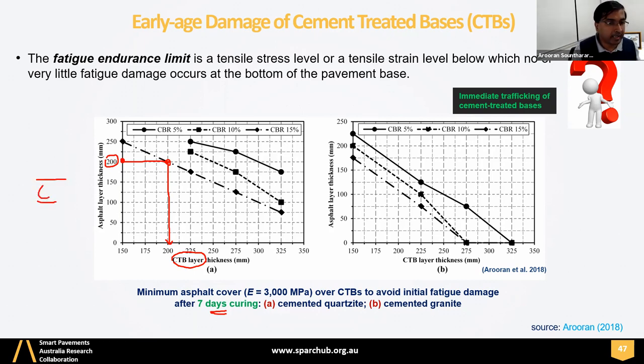that means your CTB layer is here, right? This is your cement treated base and you are constructing the asphalt here. This is an asphalt layer thickness, right? 200 millimeter. And then here, this is a subgrade, right? If the subgrade is 15 CBR, you want to construct a CTB which needs to be open in 7 days, and you have an asphalt layer 200 millimeter, so your minimum layer thickness is 200 millimeter, that minimizes the early age damage.